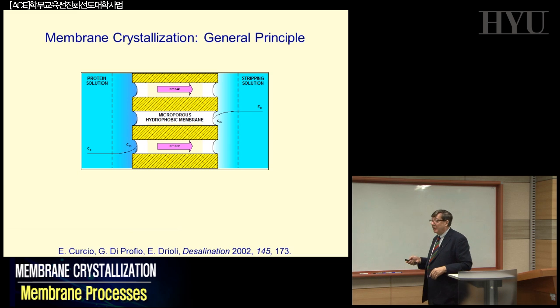That means that we can continue to have transmembrane flux at any level of concentration, eventually to the point of creating a supersaturated solution using this kind of methodology. And that was the basic idea, starting initially with, for example, protein solutions, because protein is quite interesting when trying to produce it in a very well-controlled environment, removing the water and crystallizing protein on the membrane surface, trying to reproduce what exists in nature.